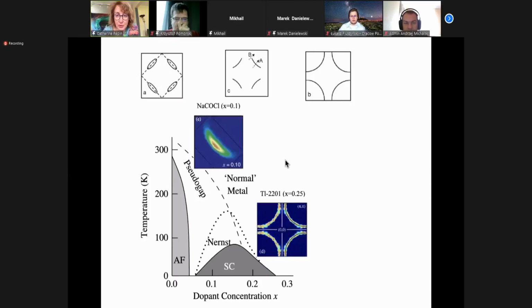So why is the pseudogap so unusual for us? Well, if you look at the band structure of the cuprates, like in this figure B, it is kind of a simple band structure. That's also one mystery of cuprates. On the left-hand side, if you dope a Mott insulator, you will get some little pockets around the antiferromagnetic Brillouin zone, which are called the hole pockets. And on the right-hand side of the doping level, this is a very big Fermi surface, which is typical of a Fermi liquid.